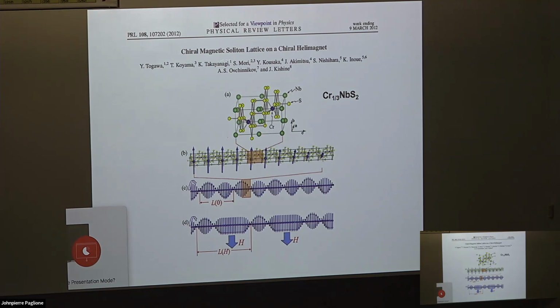So here's what's called the chiral magnetic soliton lattice. Here's the helimagnet at zero applied field. It's just the helimagnet spinning around. And then if you apply a magnetic field parallel to the planes, you form this magnetic soliton lattice. You've got these patches of ferromagnetic regions, and these are the solitons. These are like kinks, like a 360-degree domain wall. You can control this periodicity with a fairly modest magnetic field, only a few thousand, maybe 2,500 Oersted or something. So it's kind of cool stuff, actually.